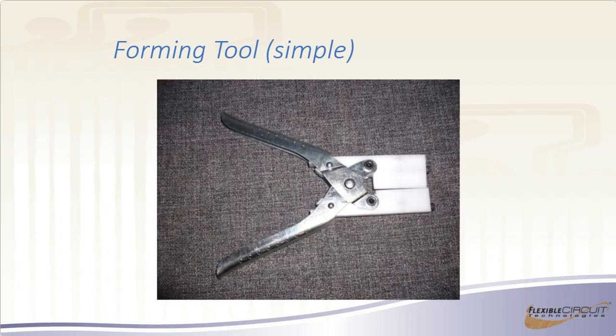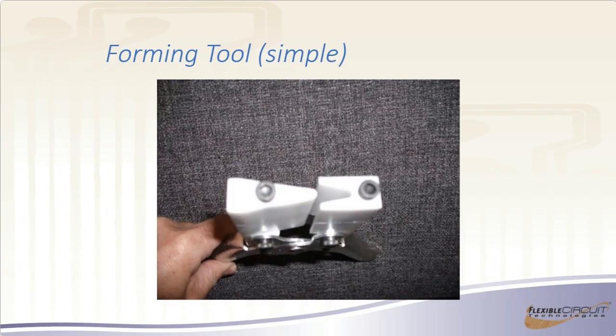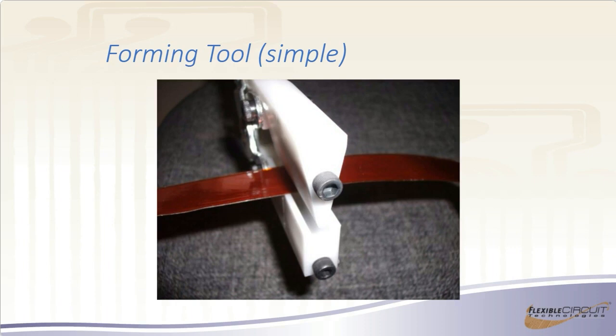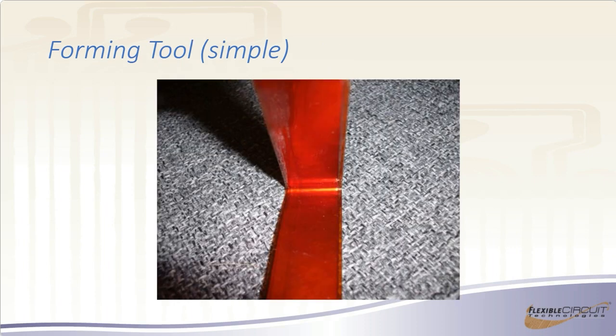This is another one. This is a little bit more elaborate, but this is just 3D printed jaws that I put on a standard parallel gap pliers. Just take into account the radius and the thickness of the circuit. When you design these, you also have to overform slightly, and you can put it in and squeeze it, and when you're done, you end up with the same form every time. It doesn't matter if it's an 80-pound woman or a 300-pound gorilla doing the work. Everyone gets the same results.